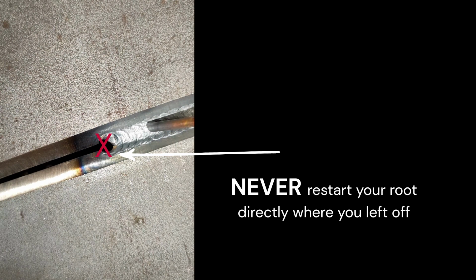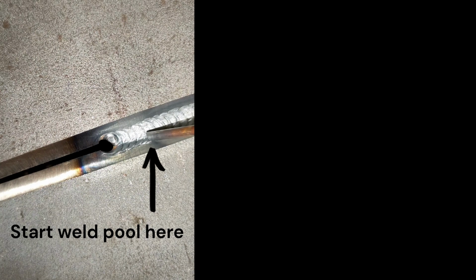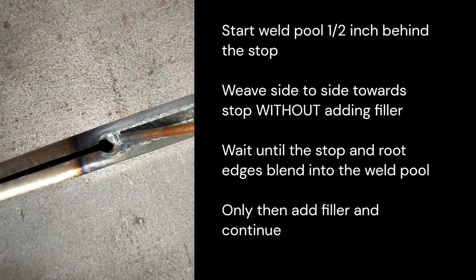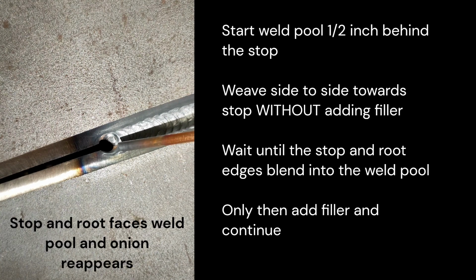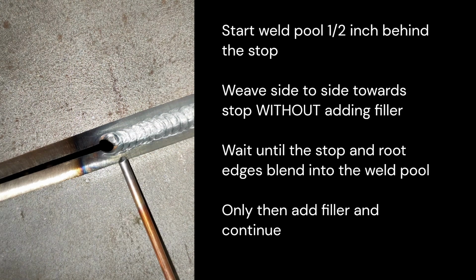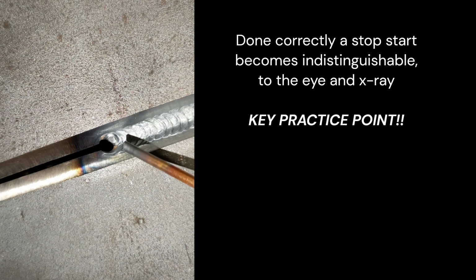You need to blend in a restart by going back half an inch, create a weld pool, and without adding any filler rod, weave the torch along the welded root slowly until you get to the restart point. Only when you can see this point become a weld pool with an onion appearing, you can add filler rod and continue the root. Done correctly, the stop-start will be perfectly blended into the existing root with no distinguishable defect, no discontinuity, or any worries at all.